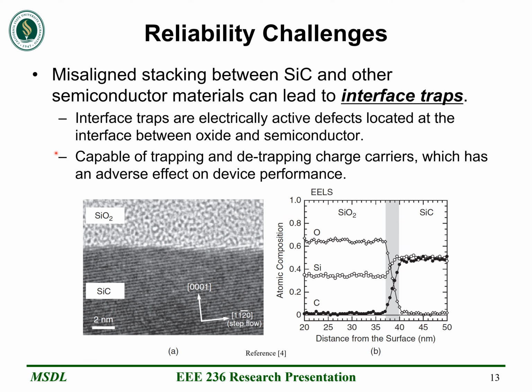So dislocations in the semiconductor material not only occur in the bulk material, but they can also occur between materials. Misaligned stacking between silicon carbide and other materials such as silicon dioxide can lead to interface traps. Interface traps are electrically active defects located at that interface between the oxide and the semiconductor. And these interface traps are capable of trapping and detrapping charge carriers, which has an adverse effect on device performance. On the bottom is a photograph of the transition between silicon carbide and silicon dioxide. And at this resolution, you can even see the silicon carbide stacking sequence. So interface traps would occur right in between the silicon carbide and silicon dioxide. And the adverse effects that these interface traps have can lead to bias temperature instability or even threshold voltage instability.